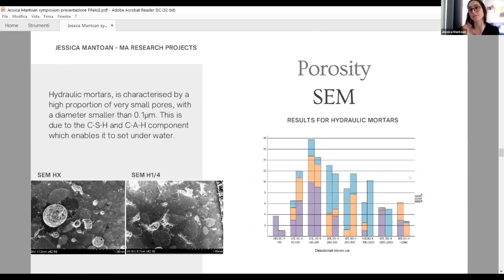Considering that hardness is always related to porosity, I decided to carry out a porosity investigation through the use of scanning electron microscopy, in order to have an idea of the topography of my sample, and in this way also be able to see the distribution, measure and shape of the porosity. Starting with the hydraulic mortar, we can see that the main difference between mortar containing barium hydroxide and mortar not containing it is that the additive decreases a lot the amount of capillaries in our mortar. That is a quite interesting result, considering that the definition of hydraulic mortar is mortar with really small pores. So that is a quite important change.